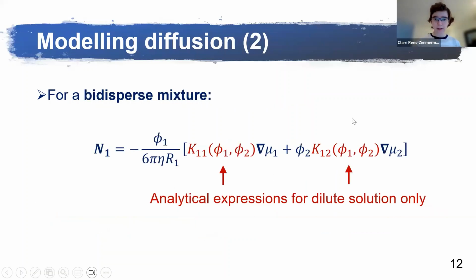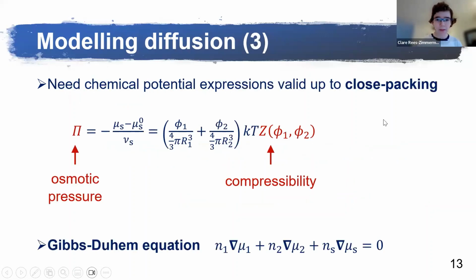My solution to this was to write the diffusive flux as shown, where you see I've invoked these coefficients K, which we call sedimentation coefficients, by analogy with sedimentation. They account for hydrodynamic hindrance. We have analytical expressions for these sedimentation coefficients only for dilute solutions, but we can extend them to functional forms which also seem physical for more concentrated dispersions. We also need chemical potential expressions that are valid up to close packing.